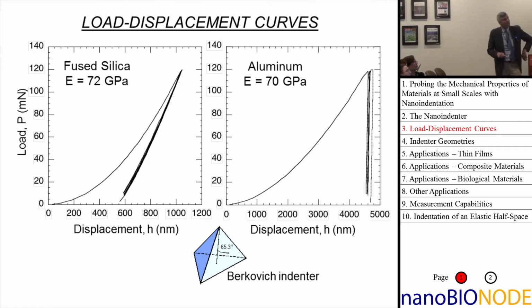All right, now, from that, we get load displacement curves. This is a load displacement curve from a calibration material, fused silica. We load up, and by the way, this indenter is this triangular pyramid called a Berkovich indenter. That's the primary indenter that we like to use. These things are made out of diamond and can be ground very sharp by the guys that used to make jewels for watches in Switzerland. They don't make jeweled watches over there unless you're buying super high-end Rolexes anymore. So they're making nano indenters instead, making lots of money doing it.